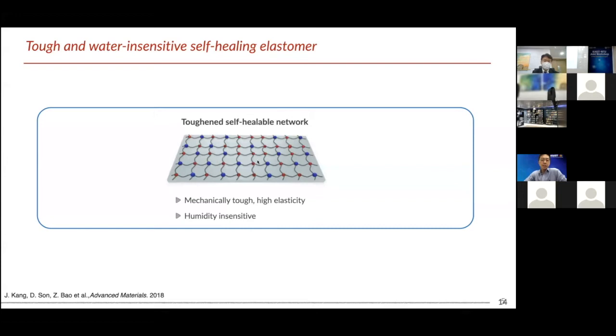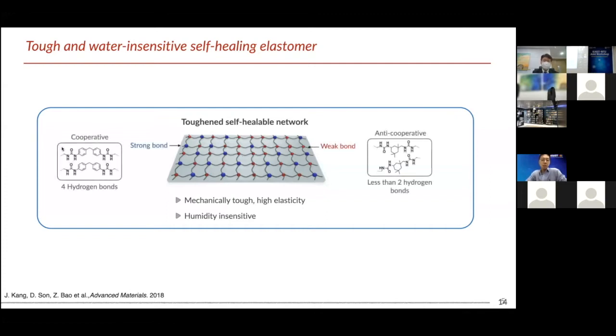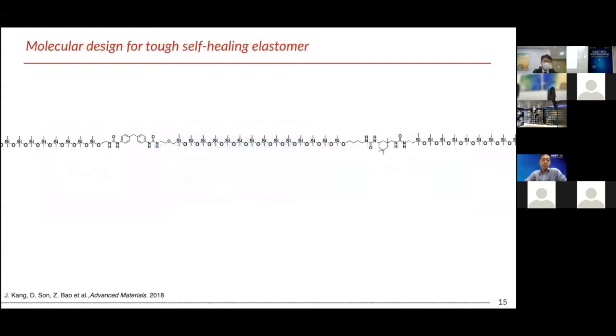Again, my supramolecular self-healable polymer network is composed of two bonds. One is a strong bond and the other is a weak bond. They have very similar molecular structures. They both have two urea groups at the ends, but the difference is the center part of the molecular structure. The polymer design is like this. We have a flexible polymer chain based on PDMS to impart a low Tg, flexibility, and stretchability.